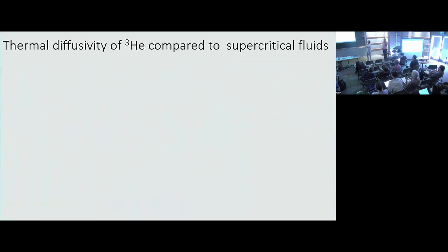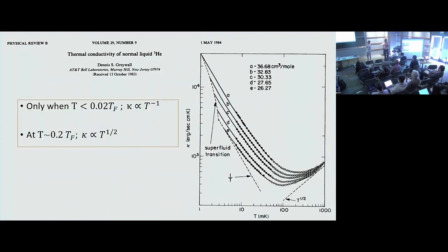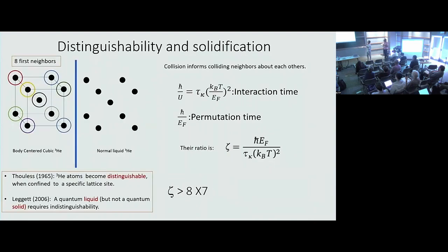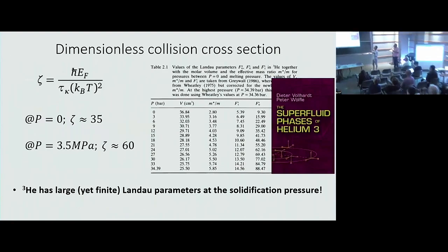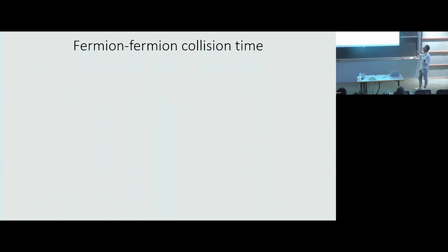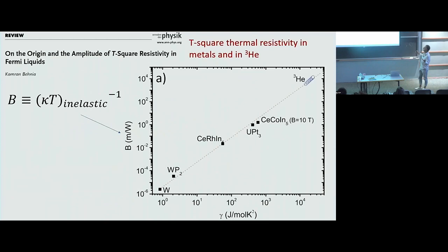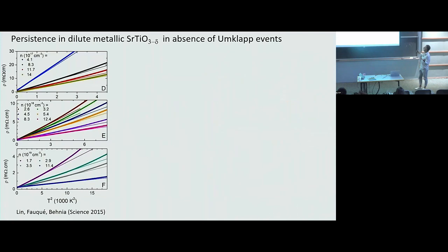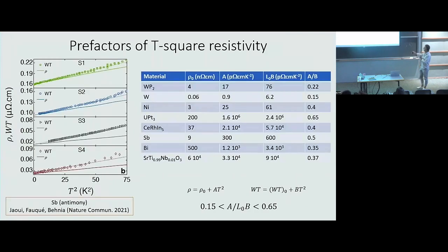So we are measuring LSCO for the moment. I have no data yet to show you. But let's say I would be surprised that you see, okay, I should go back to the table I showed you. People understand it is simply because what holds for resistivity should hold for all these guys. This has been measured by many people. Any system you look at, if you find T squared electrical resistivity, you should find T squared thermal resistivity. If not, you are violating the Wiedemann-Franz law.